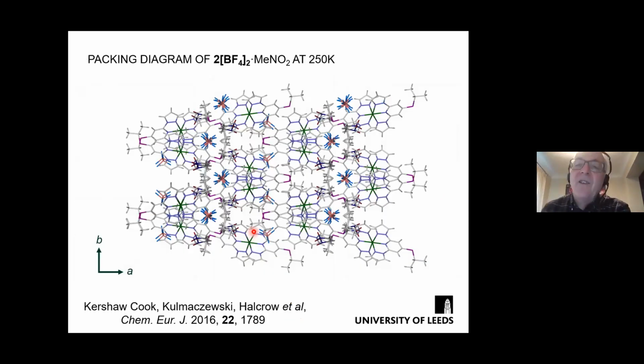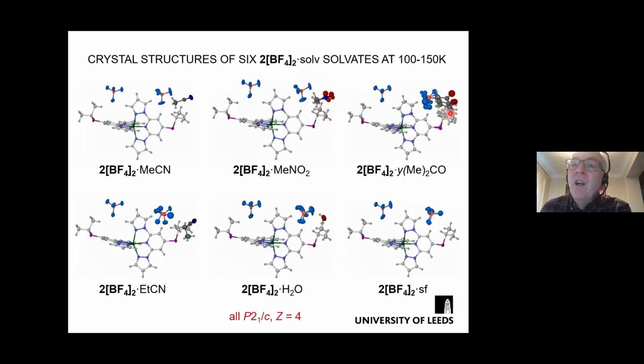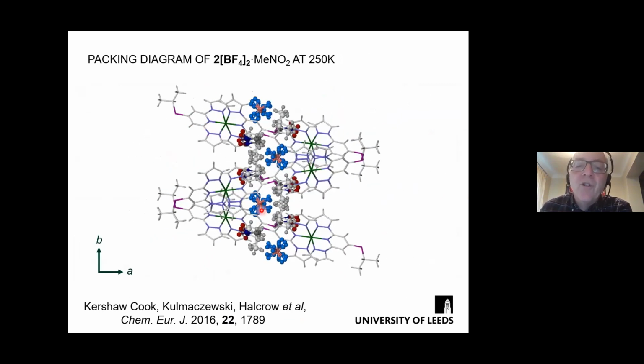And you can understand this a little bit by looking at the packing, because there's a region of the crystal lattice which is very disordered. And these are layers within the crystal which contain disordered isopropyl groups, disordered solvents, disordered anions. And if we blow that up, you can see. So you can understand maybe how the solvent molecules can slowly move past these mobile disordered residues within the layers to move up or down the layers to eventually exit the crystal.